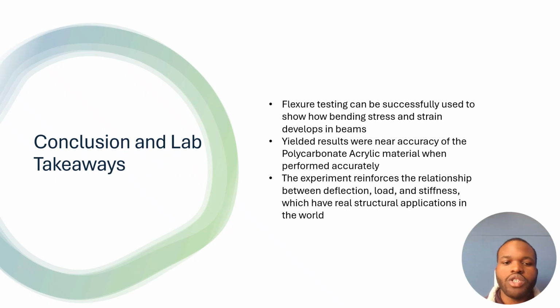And for conclusion and lab takeaways, the flexure testing properly demonstrated 3-point bending, or bending in general, and how stress and strain is seen in bending. It led us to accurate measurements of our Young's modulus for the polycarbonate acrylic material sample in both the displacement and strain gauge methods. So again, it shows that we can use either of these to get measurements. And the linear relationships of the graphs indicated how the acrylic responded. Again, the elasticity, which showed that.